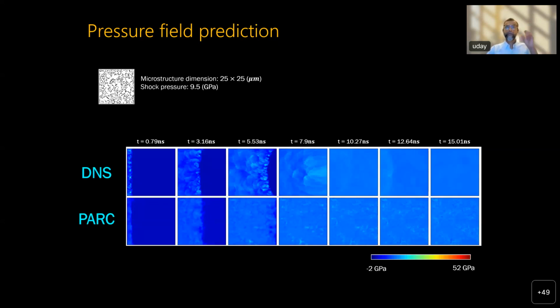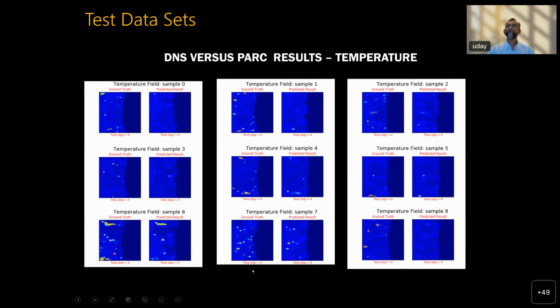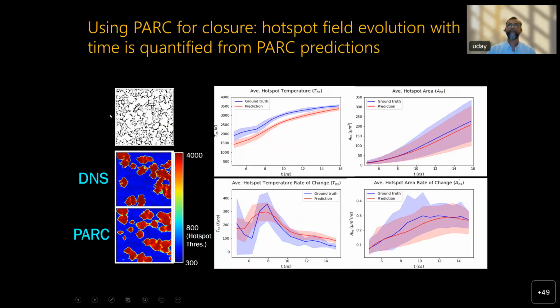So this X, and the void collapse evolution, the microstructure evolution. So this is Park exercised on many different microstructures. The left are ground truth and the right are predicted. I know it's very difficult to see this, but basically the overall message is Park predictions are in good agreement, and this is a quantitative comparison. So for various microstructures, we've run Park and we've done DNS, and the confidence intervals here are due to microstructural variability. So this is the hotspot temperature versus time, the hotspot area versus time. As you can see, in the mean and also in terms of the distribution, Park produces a good hotspot area evolution over time in good agreement with the ground truth. The rate of change of area of the hotspot versus time is also in good agreement with the ground truth. So we get the hotspot dynamics right.